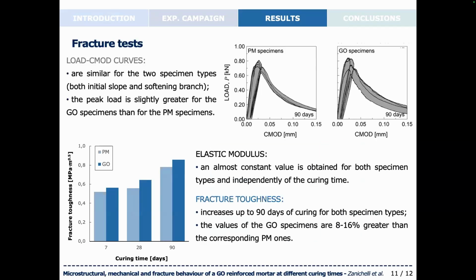And finally, the results that we obtained after performing the fracture tests. In the higher part of the slide, we have the load crack mouth opening displacement curves that we obtained testing both PM specimens and GO specimens at 90 days of curing. As you can see, the curves are quite similar to each other, both in the initial elastic stage and in the final softening branch, even if slightly higher values have been obtained for the GO specimens in terms of peak